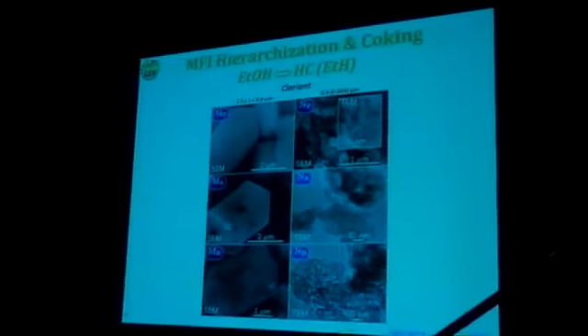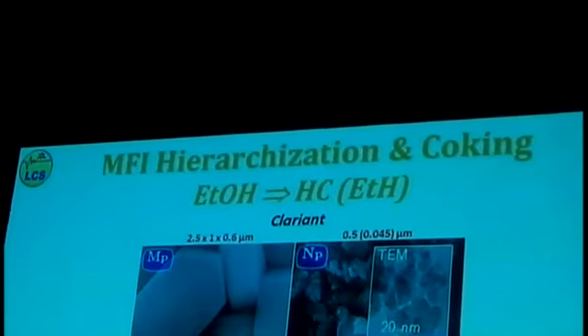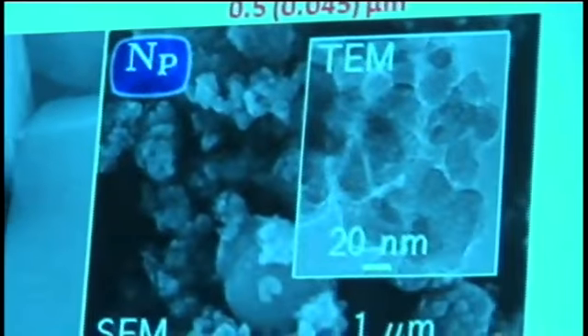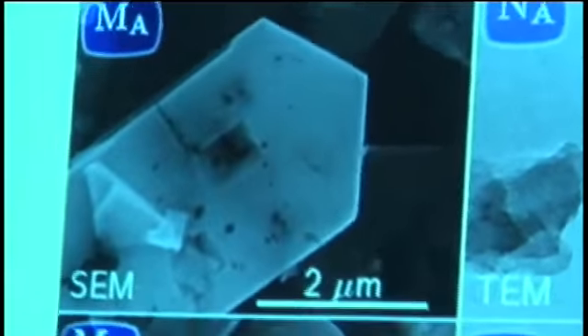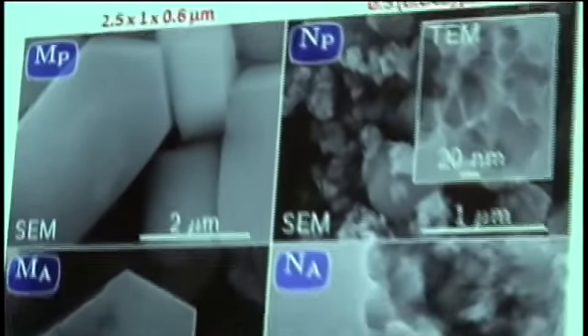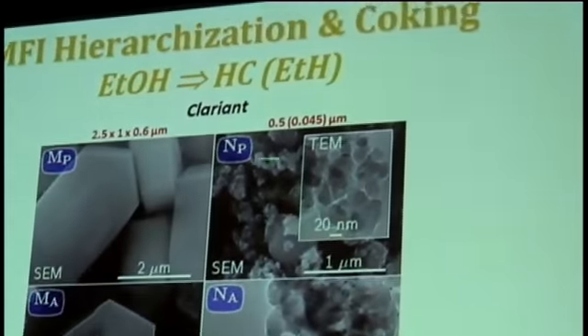So we decided to go for ZSM-5. We took one nano-sized crystal, and then we played with these micron-sized crystals. Another thing on the table that was put by the people paying the research was that we should work with commercial catalysts. So we have very good people in Caen to prepare catalysts, but we work with catalysts from Süd-Chemie, now Clariant. And so basically we took the micron-sized zeolite that will be denoted by M, and P stands for the parent. And then we took another of their materials, much smaller crystals that we are calling here nano-sized particle, and P for the parent.